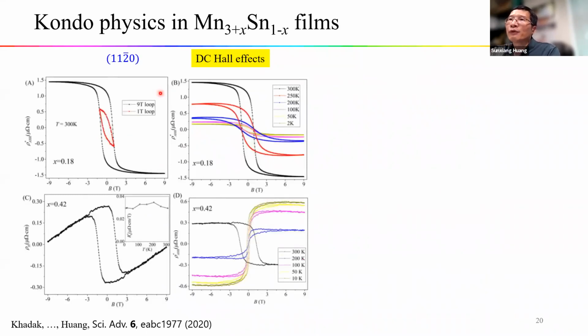We first did a DC Hall measurement for different doping samples. For the low doping one, we observed the large normal Hall effect, as in the bulk samples. This normal Hall decreases as the temperature decreases. For the highly doped one, the negative normal Hall value is much smaller than the low doped one, and it even changes sign at around 200 K.